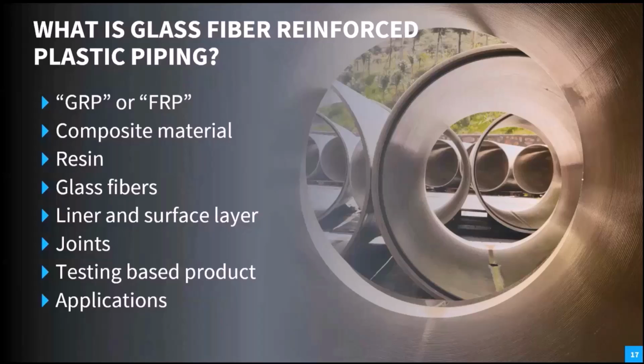According to commonly used codes like ISO standard 14692, the vendor shall set up a testing program to qualify his products and shall justify and declare the product's mechanical and other properties for further design and engineering. In general, polyester pipe is used for the lower pressure, large diameter pipe systems, like a cooling water system. Vinyl ester piping is normally used for services where a highly improved chemical resistance is required, like for example a chemical drain system. The epoxy piping systems are normally used for higher pressure and higher temperatures and or improved chemical resistance. Of course, final process and installation conditions will determine the most suitable type of composite to be used.